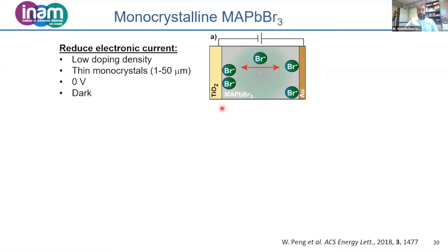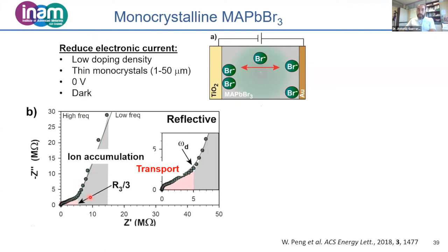They were directly grown on titanium dioxide. Because they are monocrystals, the doping density is very low. We chose crystals that were very thin, between 1 and 50 micron. And we use conditions to minimize this current, so we would use 0 volts DC bias, and we use dark conditions. And if we fulfill all these conditions, we do see the signature of ion transport and accumulation.